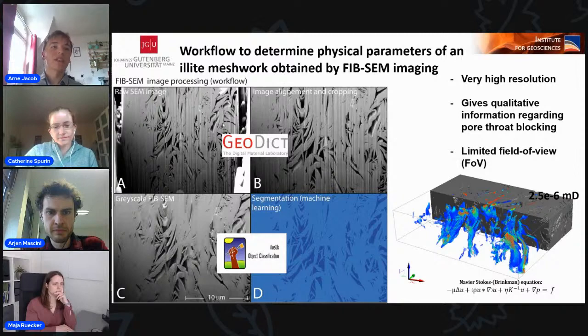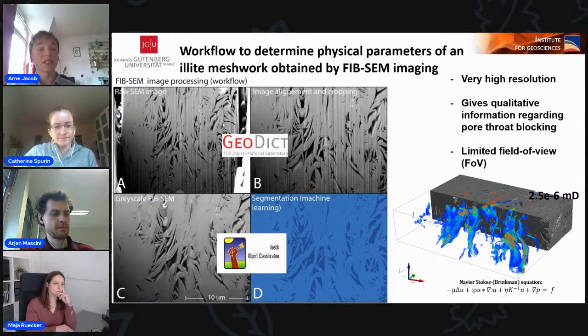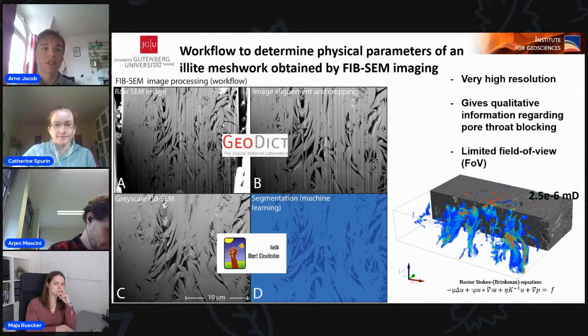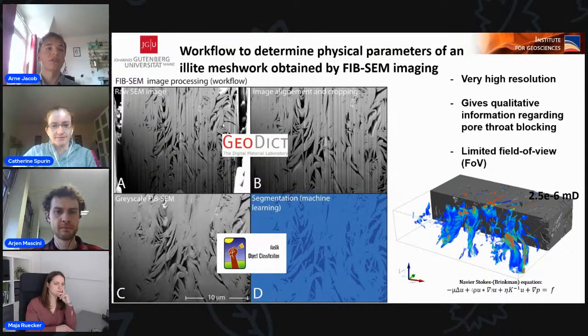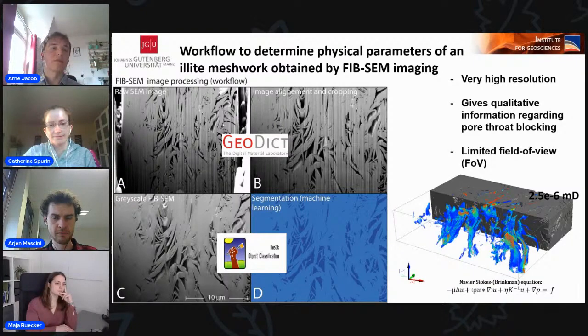While the segmentation on the original image would be very bad and noisy, one has to follow several steps to obtain a good representation of the true pore structure. First of all, the images should be cropped and aligned, while cropping is necessary since the 2D images of the FIB-SEM might contain information from outside of the structure, which you can see around this first image on the left-hand side. And the alignment can be done by using registration modules of GeoDict or other programs that can do image analysis. The stripes, which are called curtaining effect, can be removed by curtaining effect filters, which enable us to do other filtering as well, like non-local means, for example.